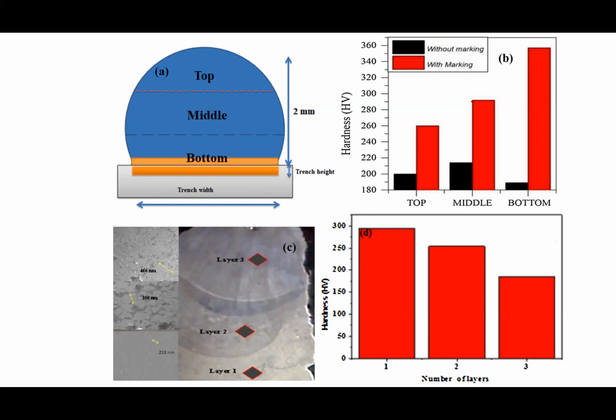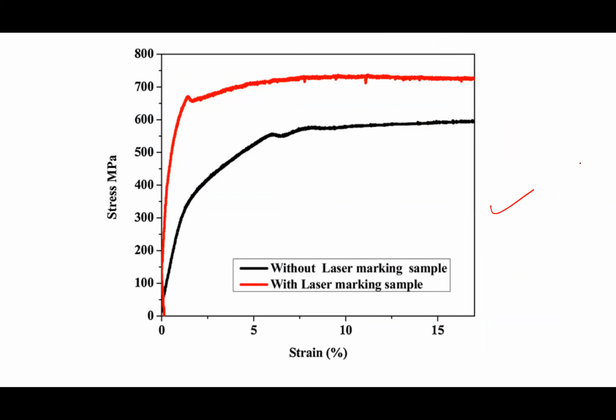So this laser treatment is done after each layer deposition for reducing the porosity and increasing the grain refinement, due to which its hardness is higher than that of the without mark sample. So in order to evaluate the bulk mechanical properties of the sample, a compression test was carried out. So in fact, this is the characteristics of a compression test.